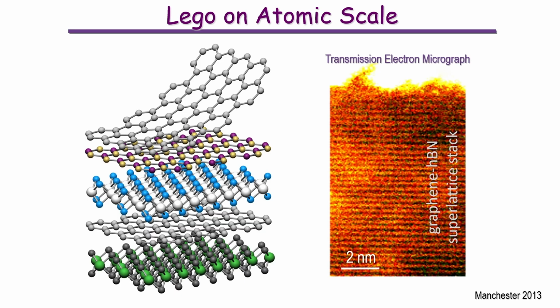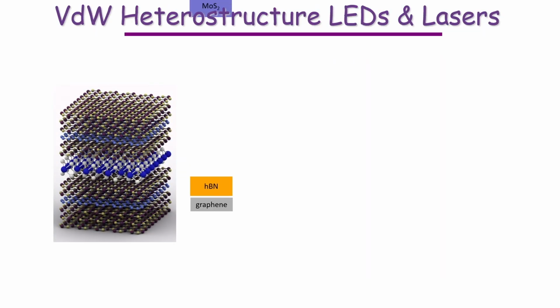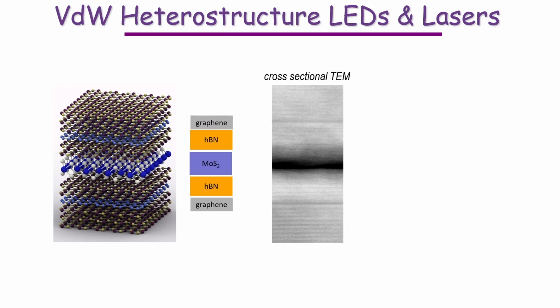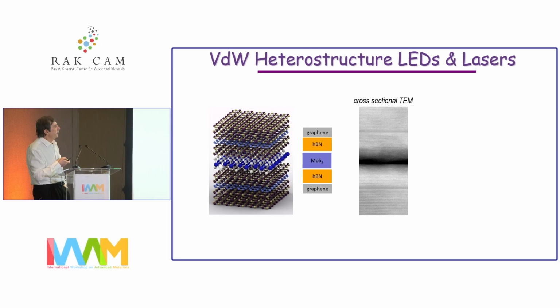Why do we do this? This is an example that we can really do this, not only as a cartoon, but in this case it's a superlattice of graphene and boron nitride. But why do we want to do this? It's a relatively simple structure which we assembled something like 10 years ago, one of the first, if not the first, heterostructures made this way. There is a semiconductor, molybdenum disulfide, in the middle. There are insulating layers of boron nitride, and there are 2 layers of graphene you can vaguely see over there, and then you apply voltage, inject current, and you get light.